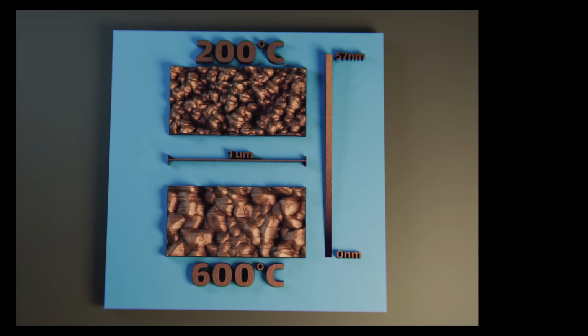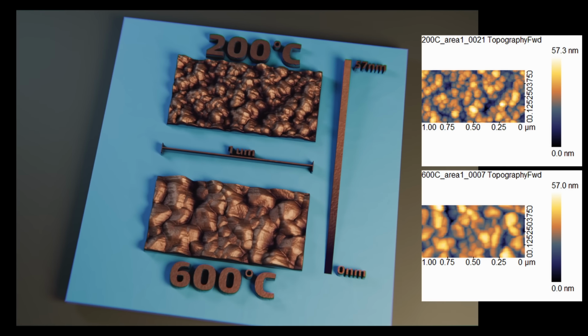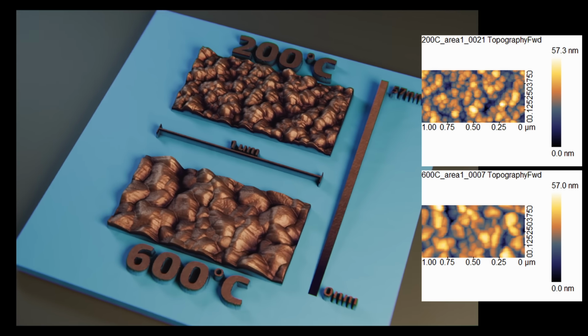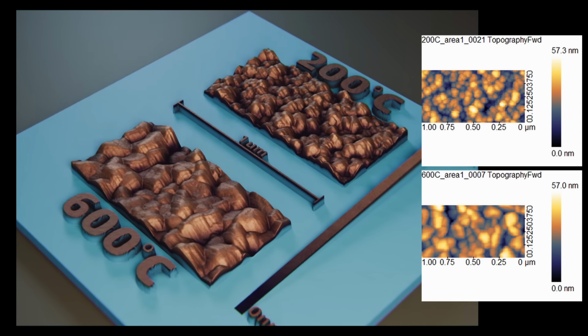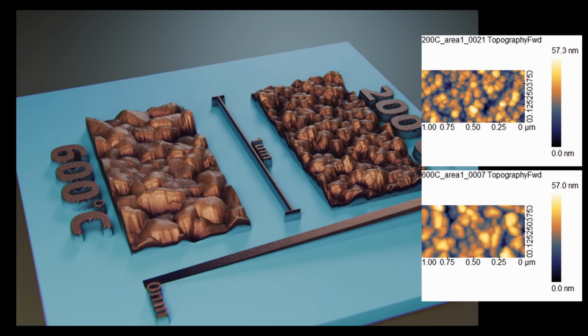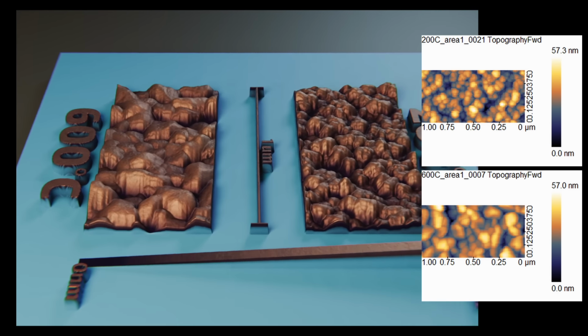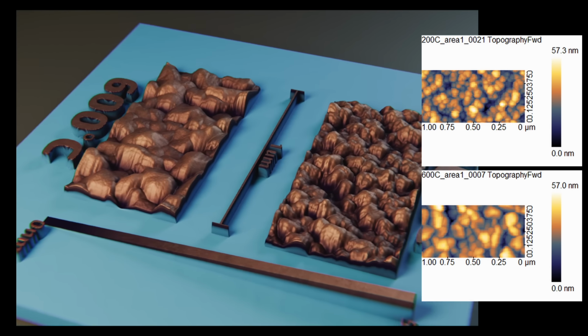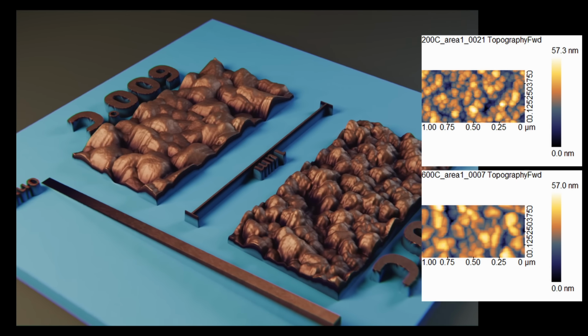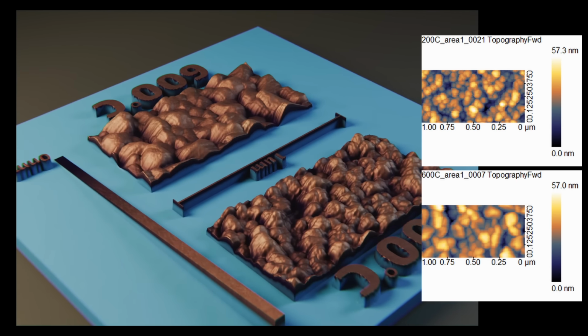But getting back on track, we have some preliminary results from the 200 and 600 degree sample that I can share today. First off, there's confirmation of a change in grain size as we'd expect. The 600 degree sample has considerably larger grains just by looking at the AFM topography. And this follows the results from the paper. We were expecting to see this.